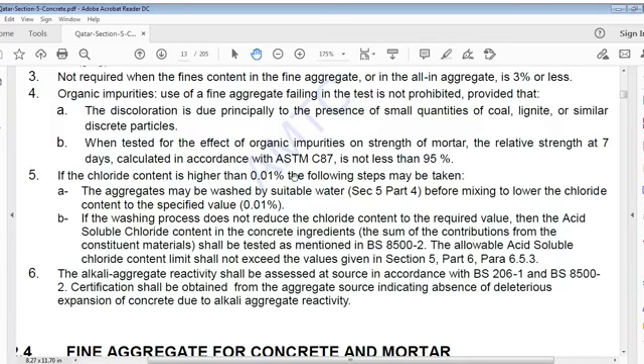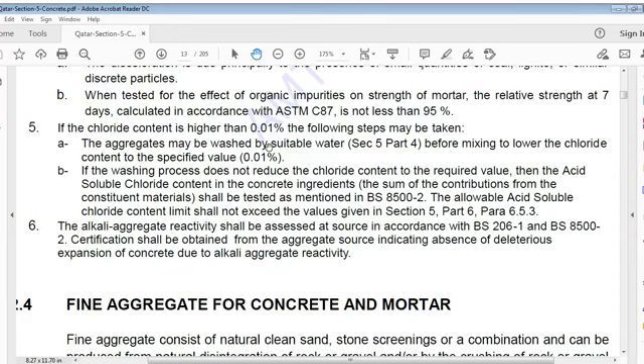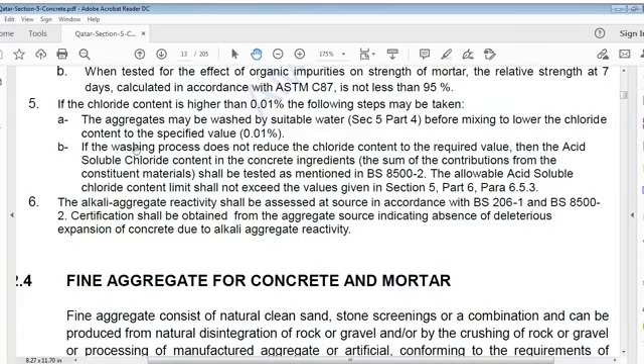If chloride content is higher than 0.01%, the following steps may be taken. Aggregate may be washed by suitable water before mixing to lower chloride content to specified value 0.01%. If washing process does not reduce chloride content to required value, acid soluble chloride content in concrete ingredients, sum of contributions from constituent materials, shall be tested as mentioned in BS 8500-2. Allowable acid soluble chloride content limit shall not exceed values given in section 5 part 6 para 653.